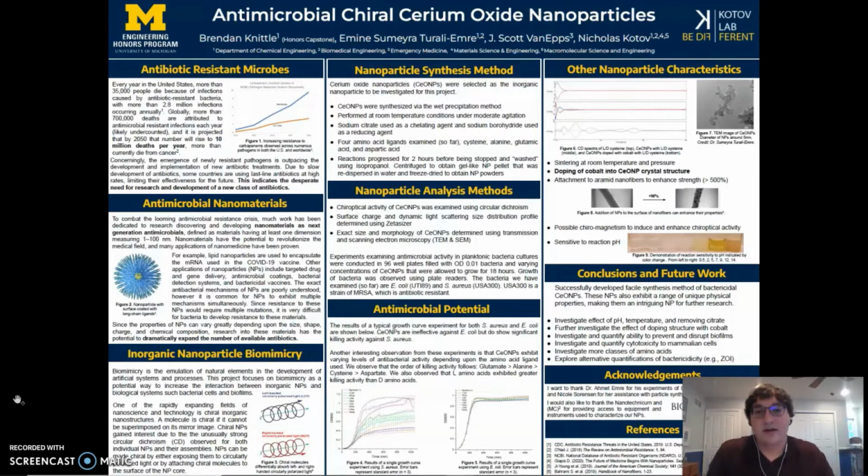Of importance is that cerium oxide nanoparticles are capable of removing reactive oxygen species from its solution. One of the mechanisms that nanoparticles use to kill bacteria is through reactive oxygen species generation. These reactive oxygen species are extremely toxic and actually will attack host DNA. So if you were to inject that into a person to treat an infection, the reactive oxygen species could attack their DNA and cause mutations and things like cancer. So we want to pursue more specific killing mechanisms that target just the bacteria, which is why cerium makes a good candidate, because we rule out the creation of reactive oxygen species.